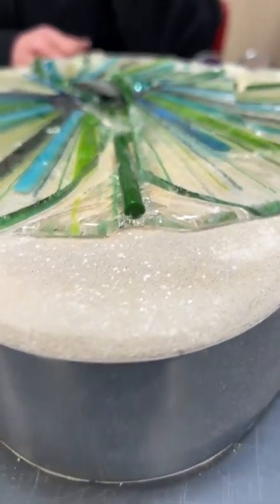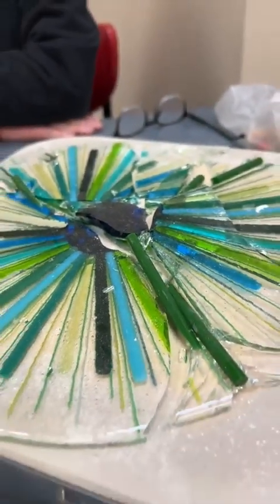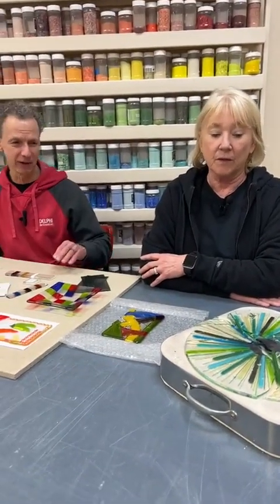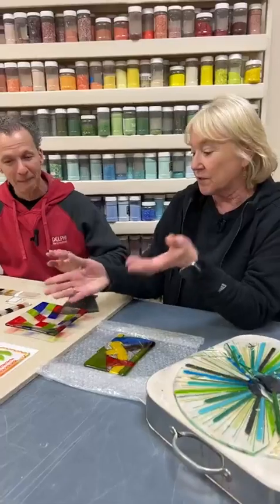And a borosilicate rod has a COE of 33. So you can see how there was just no way that baby was going to melt into this stuff. And it just popped right out. It was aggressive too in the kiln, one of the most aggressive ones I've seen, where it just popped all over the place in the kiln. So that's a real good example of where you don't need any polarized filters. Not at all. And so these are just other examples.